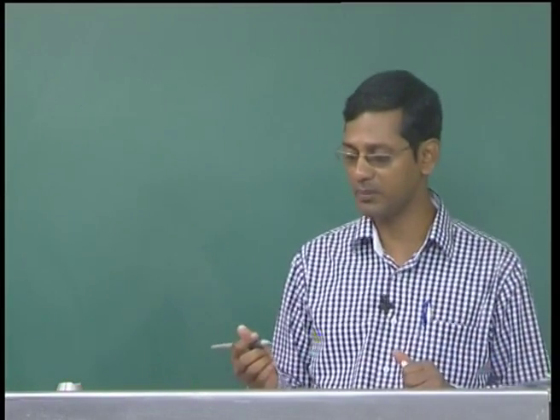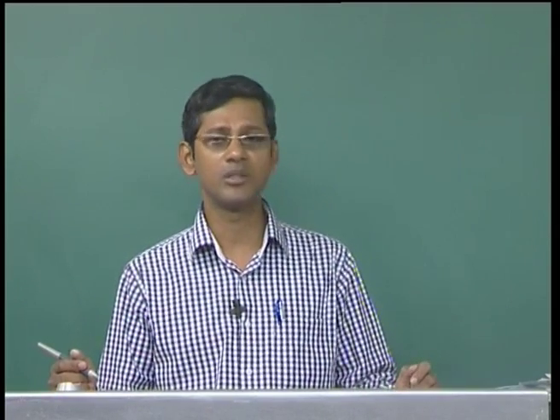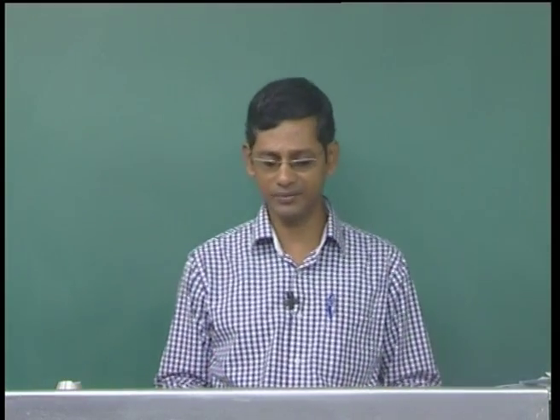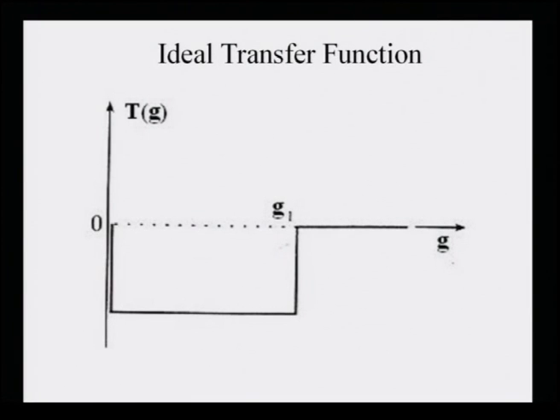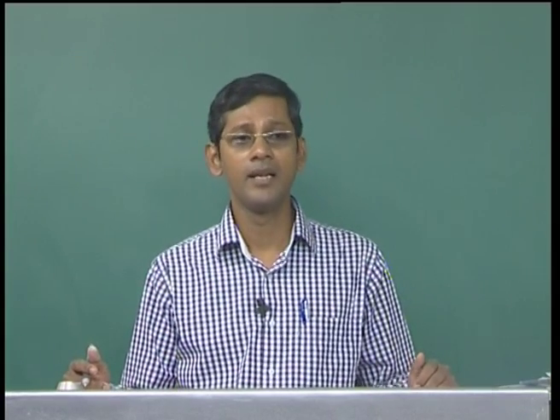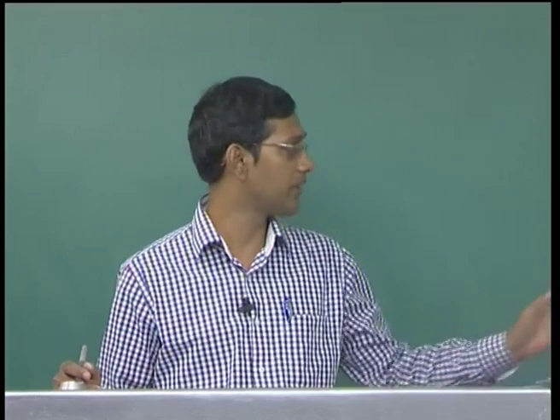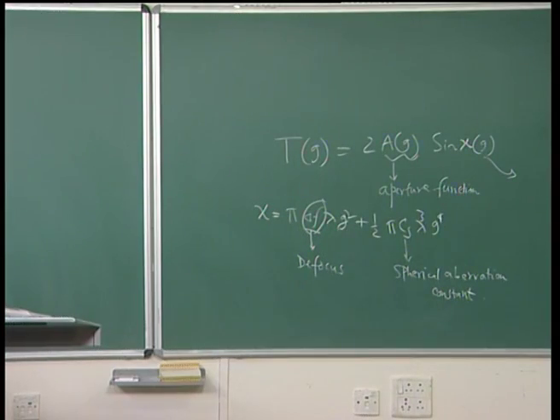So this is the slide where I am showing you the ideal transfer function when the microscope lenses are perfect. No microscope is basically a perfect one because there will be lens defects like spherical aberration, astigmatism, as well as chromatic aberration. Chromatic aberration is very difficult to correct, because the beams falling on the sample may have different energies, but astigmatism can be 100% corrected. On the other hand, spherical aberration, which is an important factor in this equation, is very difficult to correct.